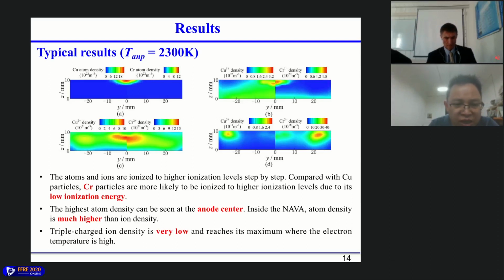And from this figure, we can see the atoms and ions are ionized to higher ionization levels step by step, from 0 to 1 to 2 to 3. Compared with copper particles, chromium particles are more likely to be ionized to higher ionization levels because they have lower ionization energy. And the highest atom density can be seen at the anode center. Inside, atom density is much higher than ion density. And the triple-charged ion density is very low and reaches its maximum value where the electron temperature is high.